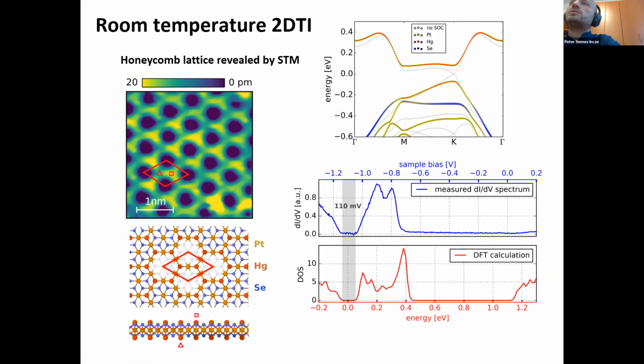One major difference, and some of the keen-eyed among you might have noticed, is that the experimental and the theoretical curves are shifted with regard to energy. So the Fermi level in the experiment is here at 0, while the Fermi level in the theory is here at 0. So the crystals in our study are basically very highly n-doped. So there's a lot of electron doping in the system, which possibly comes from defects and impurities in the crystal.